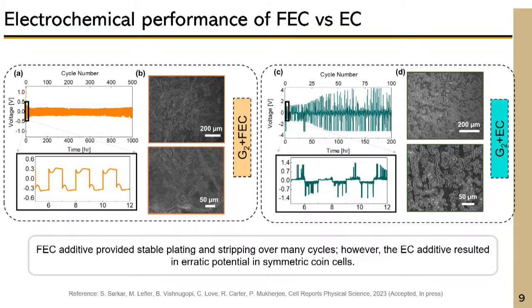Now what these results say is that stopping the dendrite is not enough - you also need to optimize. The only thing that changes when you change the electrolyte is the interface forming between your electrode and the electrolyte. So this result is saying that stopping the dendrite is not enough; you need to optimize this interfacial layer by selecting a proper electrolyte to get the best performance.